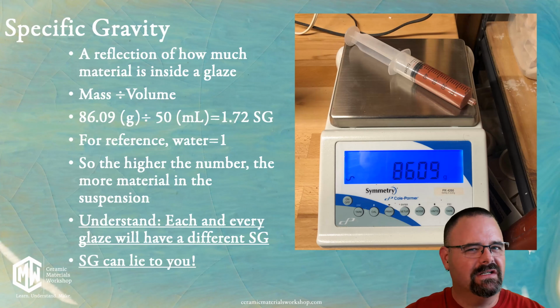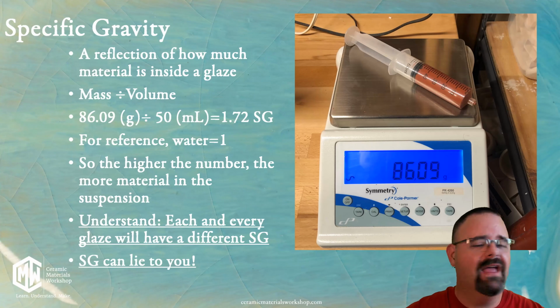Much like the fact that there's not one bisque temperature and one absorption level, there's not one specific gravity for every glaze. Some glazes are great at a specific gravity of 1.7, some are great at a specific gravity of 1.5. It all depends on the materials in the glaze and the way that you use the glaze. And on top of it, specific gravity can lie to you. Again, you have to be very careful because a lot of people will go around saying, oh, specific gravity, that's what you need to know. That's how you keep a glaze consistent.